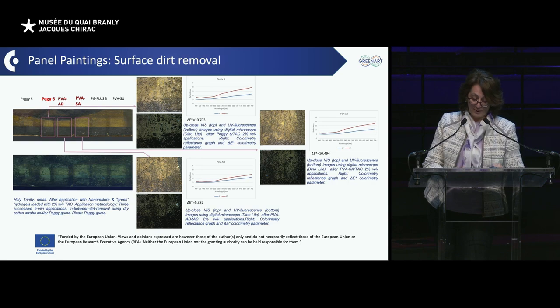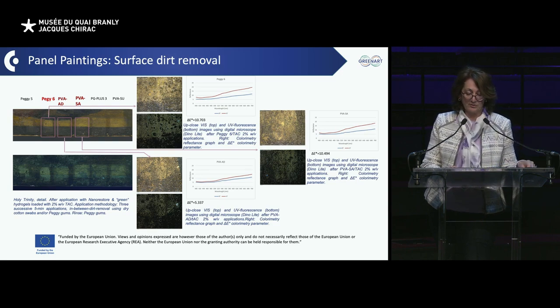When we are evaluating cleaning methods, especially on delicate surfaces, we need precise tools. We started with UV fluorescence photography, which, as you can see in the second image at the left, gives us a good initial sense of dirt removal. Brighter fluorescence generally indicates a cleaner surface. For instance, notice the clear difference with the Peggy 6 application. It shows a significant reduction in dirt.